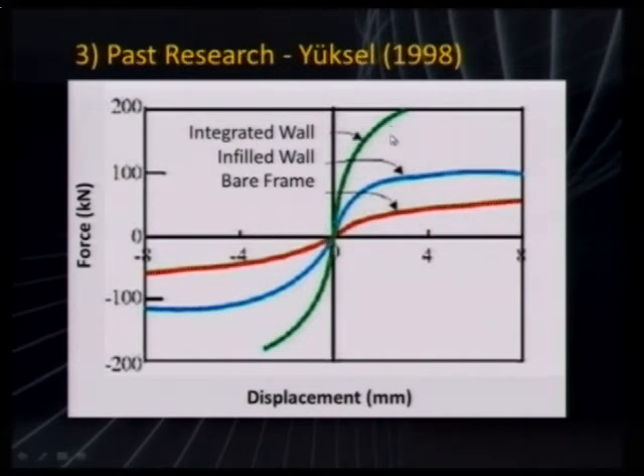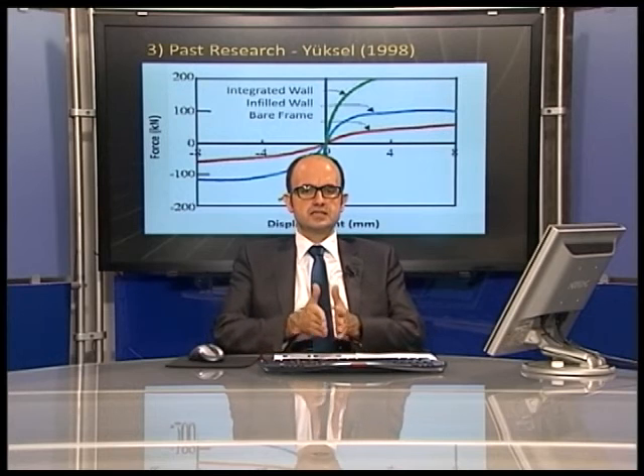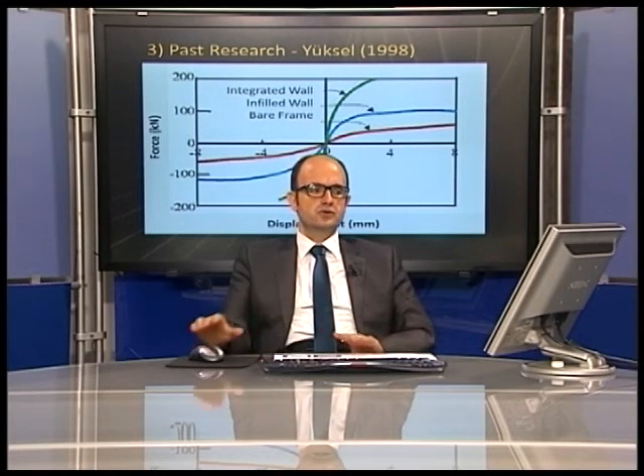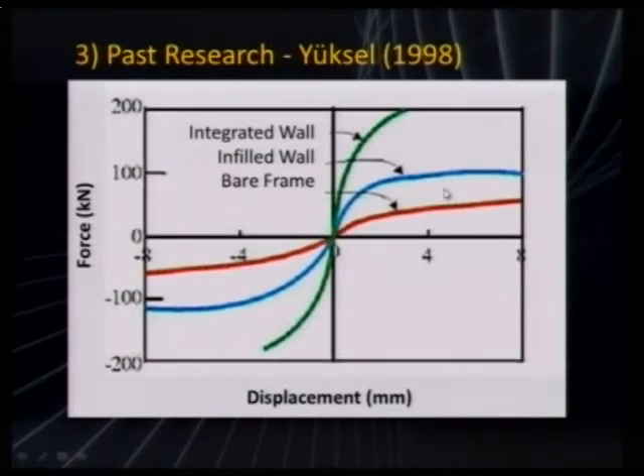We can see here that when we compare the force displacement behavior of the bare frame and the infill wall, there is a large increase in strength and also in the stiffness of the structure. In the infill wall, there are no torsional effects. The only motion is in its own plane, so there is no sudden decrease in the forces. There is good ductility of the structure with the infill wall.